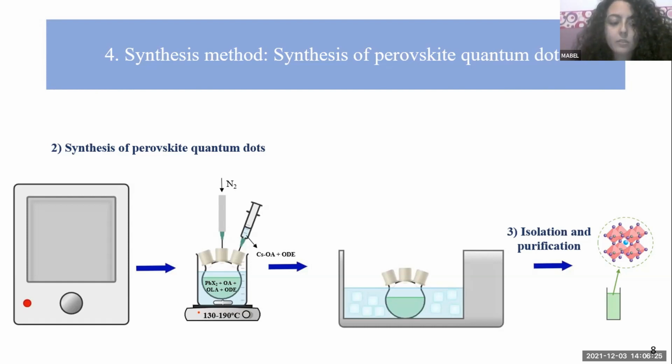In the case of palladium-doped cesium lead tribromide quantum dots, it was not possible to obtain the precipitated quantum dots by centrifugation, evaporation, or by drying under vacuum. For that reason, the colloidal suspension of perovskite quantum dots was kept in octadecene.